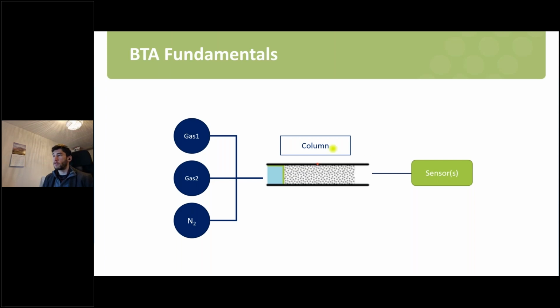You have a column of a material, which is a packed column, and you're introducing one or more gases or vapors or mixtures. And at the end of the column, there is a sensor that monitors concentration. So you can think, you have a step change in the concentration from nitrogen up to 1% of CO2, and you're measuring how long it takes for this to reach the end. When it reaches the end, you can calculate the amount adsorbed onto the material in the column.